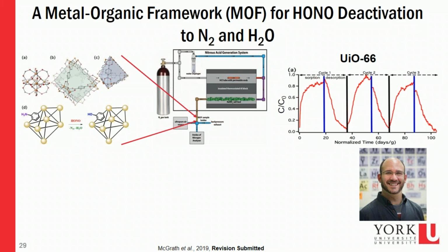This is a collaboration that I got involved in while I was at Boreal with metal organic framework chemist Mike Katz, and in collaboration with Corey Young as well. We call him the MOF Father. This is something he likes to be called. So how these work: you have metal nodes that you create a porous network with by bridging them with organic linkers. You can create very well structured pores that can be hexagonal, bipyramidal, or tetrahedral, or you can stack them together into these highly porous crystalline substances. Those organic linkers, if you chemically modify them, can then allow you to control some chemistry that can happen within the pores.